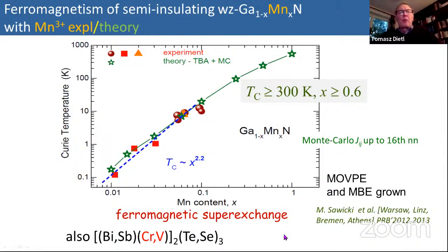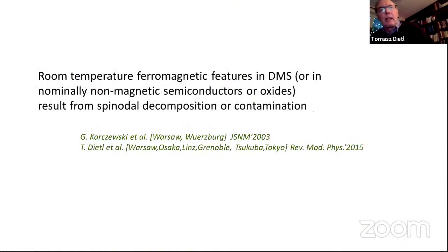It's interesting to know, for those of you who are interested in ferromagnetic topological insulators, that the same mechanism of ferromagnetic superexchange operates, of course, also in these chalcogenides, bismuth and antimony chalcogenides with chromium and vanadium. So this is a very interesting and general mechanism of coupling without carriers. And also you can see, on the logarithmic scale, that if you have a concentration of manganese above 60%, you cross room temperature. So if you would manage to have, locally or macroscopically, a manganese concentration as high as 0.6 or higher, then you will cross room temperature.